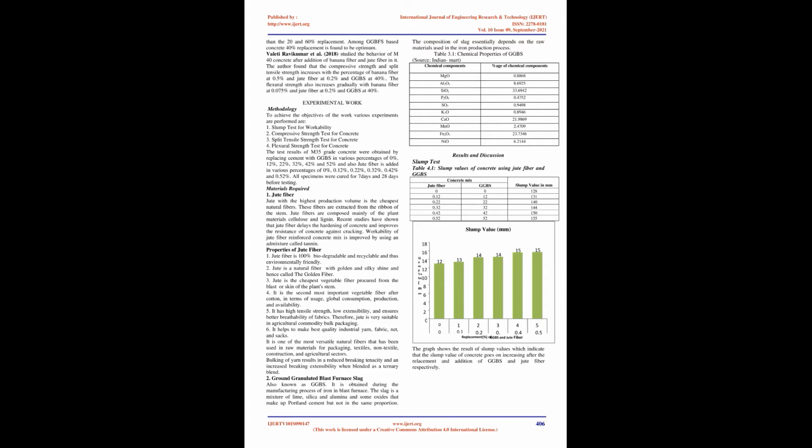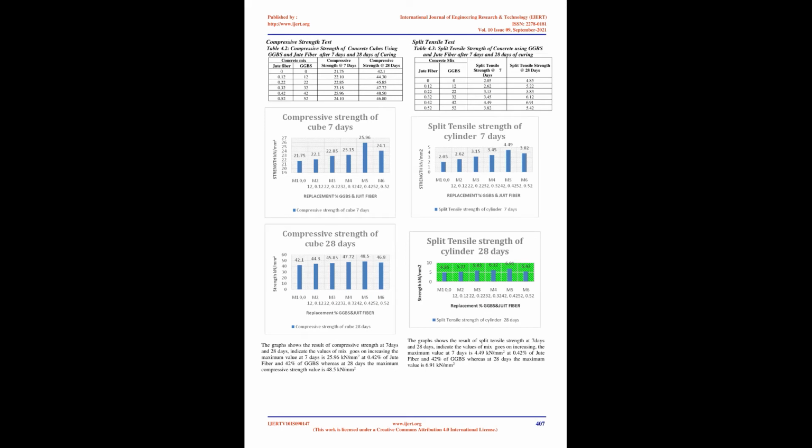S. Tiwari et al., 2020, studied mechanical properties and durability of jute fiber reinforced concrete. The results show that the workability indicated that the slump value reduced as the amount of jute fiber in the concrete specimen increased. Also, compressive strength reduced in acid curing as compared to normal curing. Additionally, jute fiber increased the compressive and tensile strength of every concrete mix.